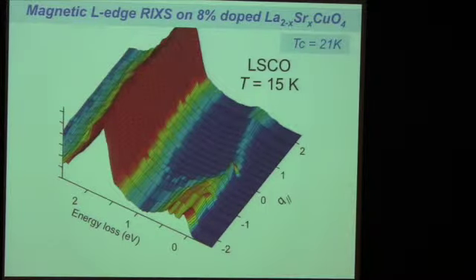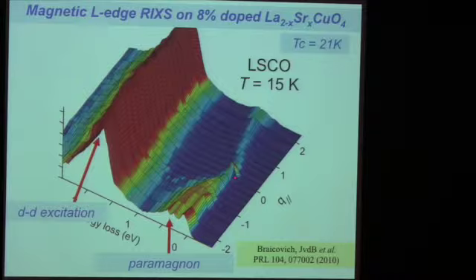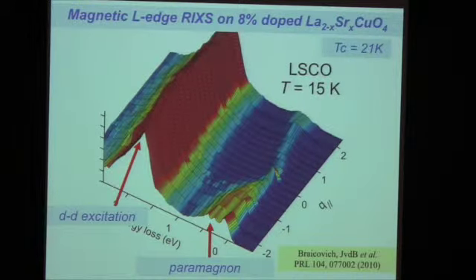Tc is an energy scale that's not relevant for this spectrum, because here you see energy losses in the order of eVs, and here's the momentum transfer. What you see at 2 eV, again, is this dd excitation that we have seen already a couple of times. It's not momentum dependent, and it's sitting there in the doped system just as it was sitting there for the undoped system. Okay, but now let's look at the low energy scale. This looks like a magnon that is dispersing. It doesn't come with the label magnetic, but it's an excitation that's dispersing just as the magnons were in the undoped system, but now in a non-magnetic system, in a paramagnetic system, actually in a superconductor.